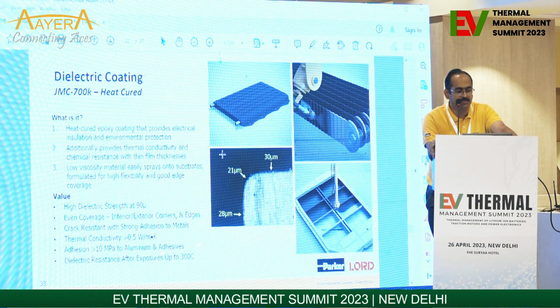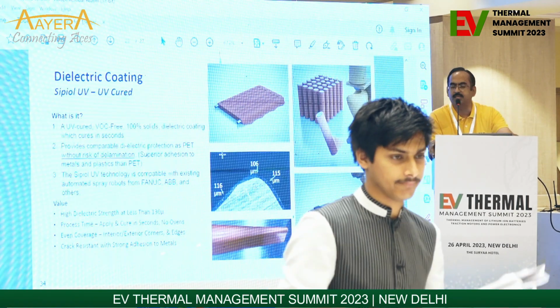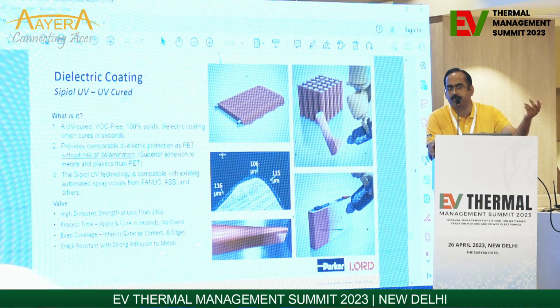This is a product, JMC 700, which is a heat curable product, cured at 180 degrees centigrade for 20 minutes. And we have another coating which is UV curable. So if you have a high volume of production, your material can be cured within 15 or 20 seconds. That is the Sipiol UV coating, which has 100% solids. The prior one was a solvent-based product. This is a solventless product, so a 100% green product, which is UV curable with high dielectric strength at less than 130 microns of thickness.